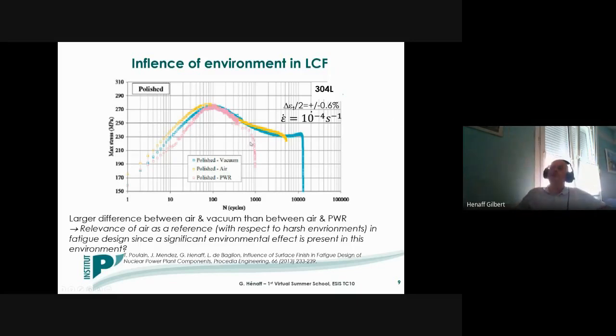France. And so as expected, first, what you can see is that globally, the cyclic stress-strain response is not affected by environment, but we have an effect of environment on the fatigue life. And as expected, in the PWR environment, the fatigue life is much less than in air. However, if we compare air with vacuum, you can see that the difference in terms of number of cycles is much larger between air and vacuum than between air and PWR environment. So that means that environmental effects are already present in air and have a large effect on the fatigue life.